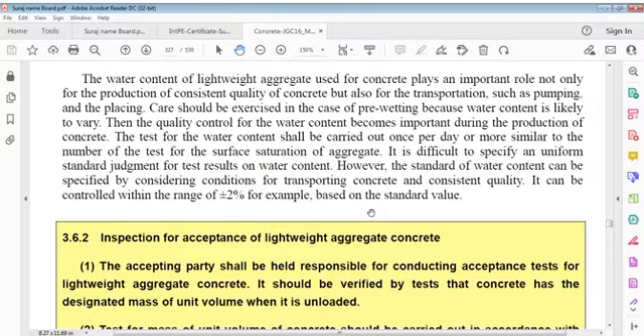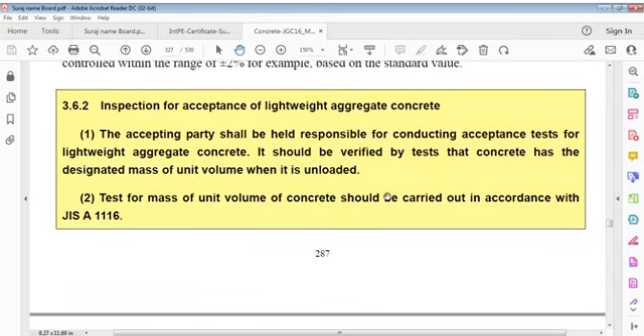Test for water content shall be carried out once per day or more, similar to the number of tests for surface saturation of aggregate. It's difficult to specify a uniform standard judgment for test results on water content. However, the standard of water content can be specified by considering conditions for transporting concrete in consistent quality. It can be controlled within a range of plus or minus 2%, for example, based on a standard value.